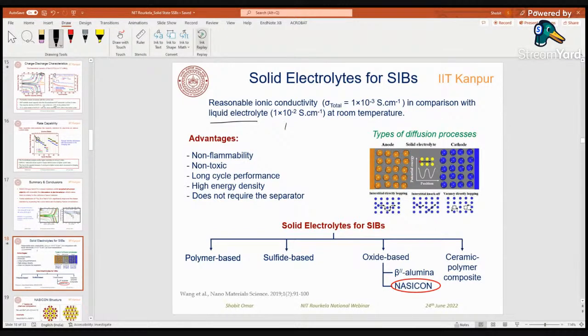Okay, so there are different types of solid electrolyte which have been tested for sodium ion battery, and here I have classified them. First one is the polymer base, like PEO, right? But the problem is it shows very poor ion conductivity, sometimes in the range of 10⁻⁵, or I can say 0.01 millisiemens per centimeter. So if you want to increase the conductivity of the polymer, you have to increase the temperature of the battery cell if you are using the polymer based electrolyte.